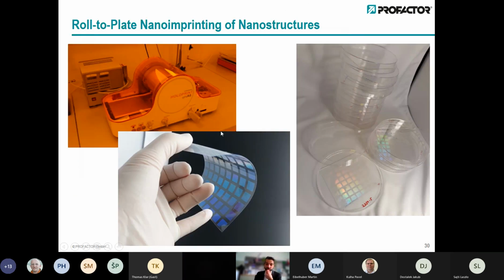So if you want to go to even larger areas, you can take such a sample, which was step and repeat printed, and make one large printing plate from it. And for example, use this in a roll-to-plate nanoimprint tool and do an imprint of the full area in one printing step. Then you can end up with many, many samples, which is, for example, also relevant if you want to have many nanoparticles for the biosensing example I showed earlier.